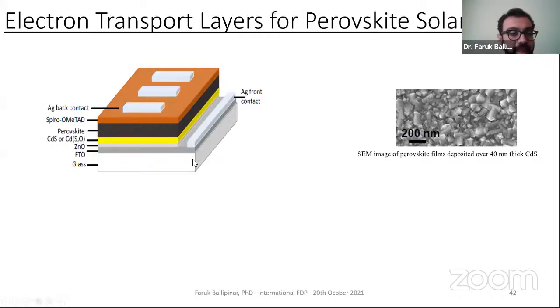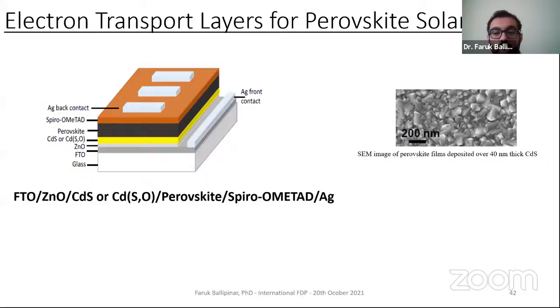In my perovskite solar cell, we use this structure: perovskite, Spiro-OMeTAD, and between FTO and silver back contact. Our electron transport layer is cadmium sulfide or cadmium oxysulfide. So from this research, the optimization of the electron transport layer and implementation of cadmium sulfide and cadmium oxysulfide for perovskite solar cell as well.